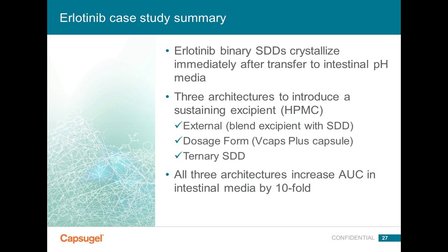Let's summarize the Erlotinib case study. In the case of Erlotinib binary SDDs, they dissolve to a fairly high extent in gastric media, but then they crystallize immediately in intestinal pH media. So we have three architectures that help us to introduce a sustaining excipient. We have external, in which we blend the excipient with a binary SDD. We have using the dosage form, meaning an HPMC V capsule, or incorporating all three components in a ternary SDD. And all three of these architectures have been shown to increase AUC in intestinal media by at least 10-fold.